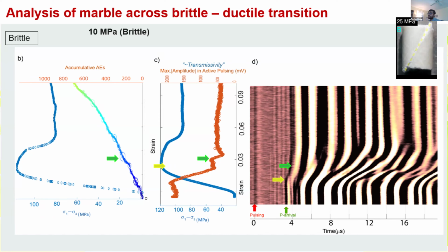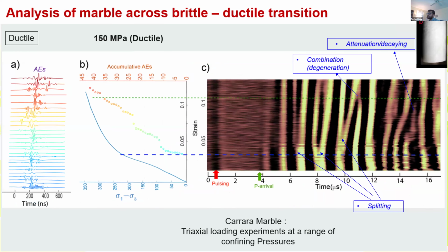And just to see how different this is compared to more of a brittle regime to ductile, here's the example for a ductile regime. So this is at 150 MPa. Again, we see a lot of interesting changes in the coda. And that's a lot more dominant and clear as opposed to looking at changes in the p-wave velocity. So the p-wave velocity maybe slightly changes, but it's not so distinctive. And partly in this case, we don't have a clear yielding phase. It's sort of a continuous yielding as you're going from purely elastic to semi-brittle to then sort of plastic deformation behavior. So it's features like this.